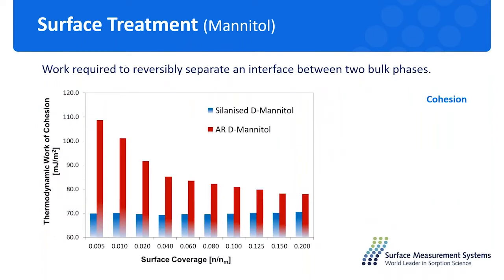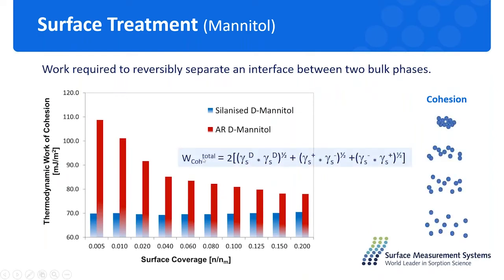And when we have the surface energy of the material, we can also apply this equation to calculate the cohesive work between the particle and the particle by the surface energy components. So we have the dispersive surface energy and different components of the specific surface energy. So we can calculate the work of cohesion of each particle, the untreated and the silanized. And if the surface energy is higher, basically the work of cohesion will be higher as well. And a higher work of cohesion is always indicative of a higher aggregation tendency of the particle itself. So basically the particle-particle interaction is much stronger, which will cause the aggregation of the material.